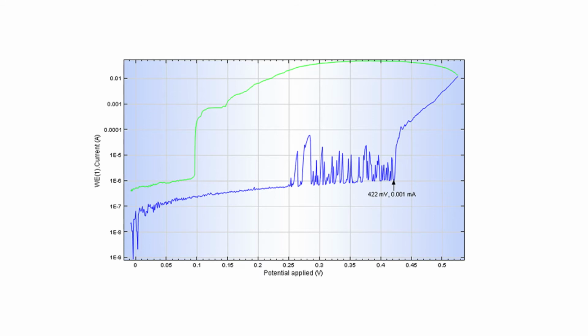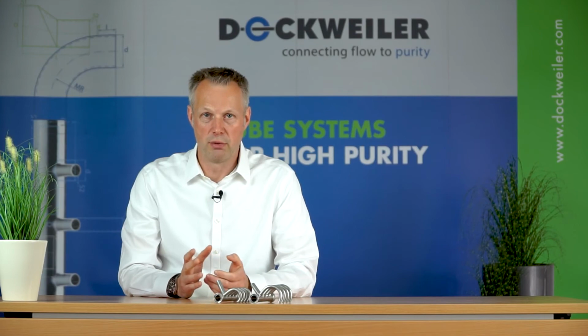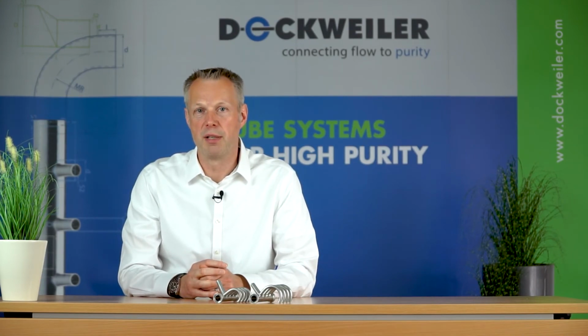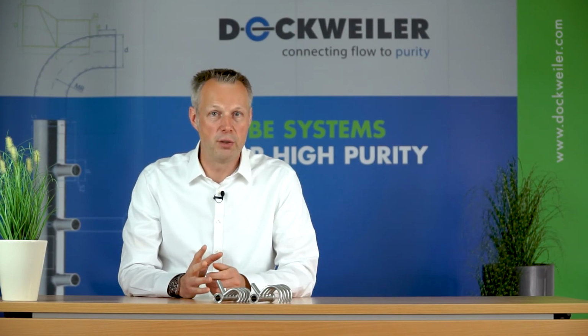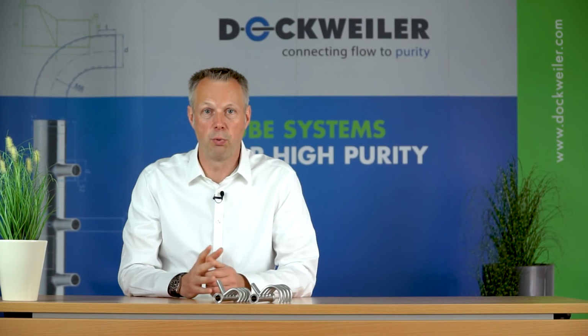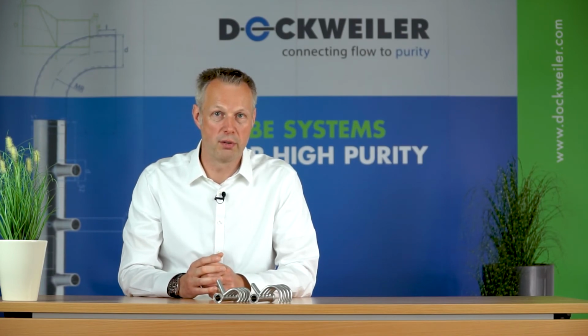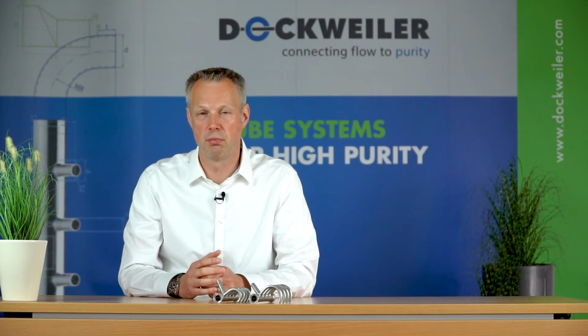However, those defects, those impurities will disappear again, and the surface will repassivate. That's what you can see as the current is dropping down again to a certain base level. This number, or this effect, is the critical pitting potential. And when you use a certain material, a certain surface, then you will get a certain value of it. That is a quantitative value for the resistance towards corrosion.